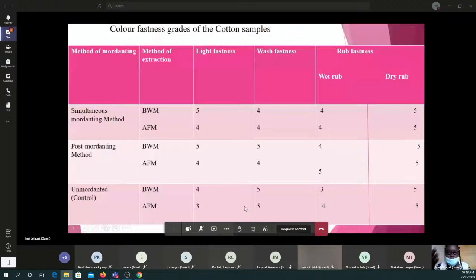When you come to rub fastness, two trials were tested, that is wet rubbing and dry rubbing. On the control, that's the ammonia fermentation method, it improved to excellent on post-mordanting. And also, it maintained a good grade on simultaneous mordanting. When you look at dry rubbing, all the grades tested 5, which was very good.